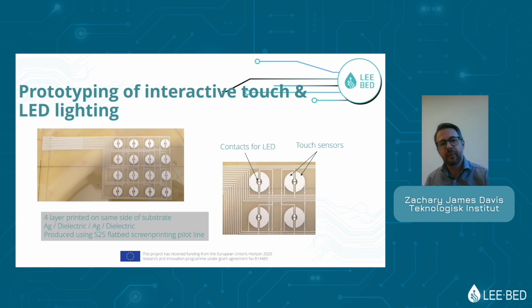This is an example of a collaboration where we were trying to make capacitive touch and LED lighting on the same foil, and this is done on a PET foil, a plastic foil, with four layers printed on the same side of the substrate, silver and dielectric, using a sheet-to-sheet flatbed screen print process. We also used a digital inkjet process for the prototyping phase, and then made the pilot production using a screen printing phase.